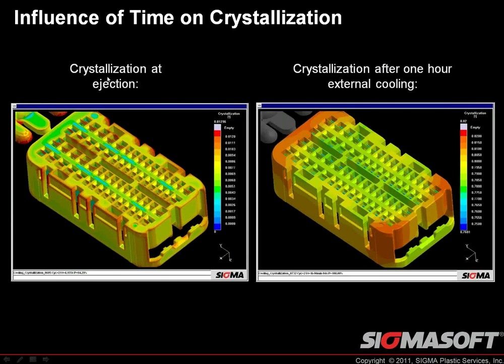Related to that, crystallization is one component. At ejection, very little crystallization has occurred, so there's a lot of cooling and crystallization that still needs to happen. After cooling, it jumps up significantly — about 82 percent crystallization versus almost zero at ejection.